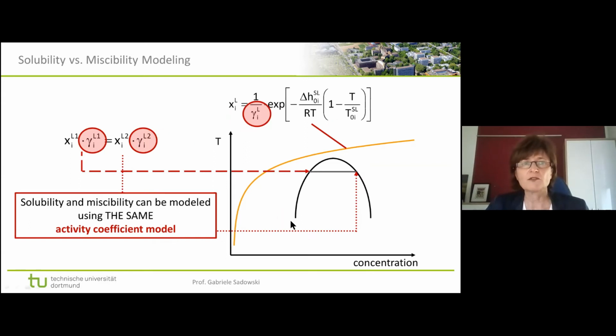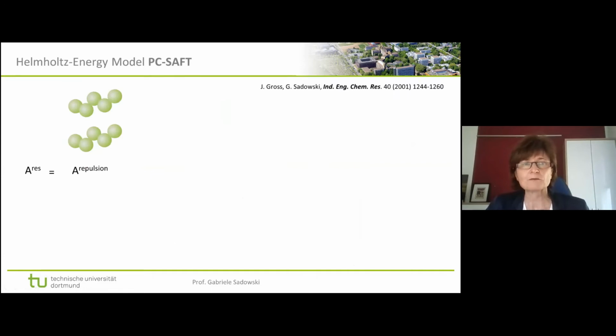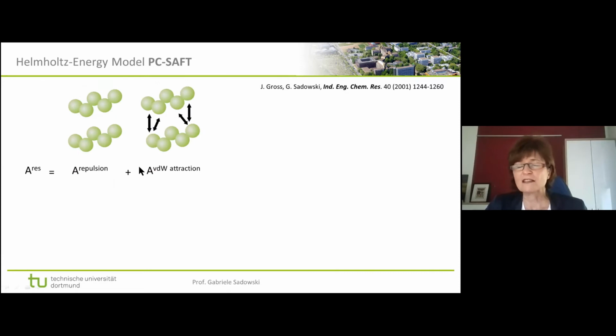The model we are using for this purpose is PC-SAFT. So that means we have the Helmholtz energy of a system, and once we know that, we can then derive with respect to the mole number of the different components, and then we get the chemical potentials, and from that we get the activity coefficients. And PC-SAFT as such is a Helmholtz energy which is composed of different contributions. So we have a repulsive contribution that accounts for the fact that the molecules have a volume, and also for the fact that they are not spheres, but have more of a chain-like structure. Then we have a van der Waals attraction term, which accounts for the fact that molecules also attract each other. And so this is a second contribution.